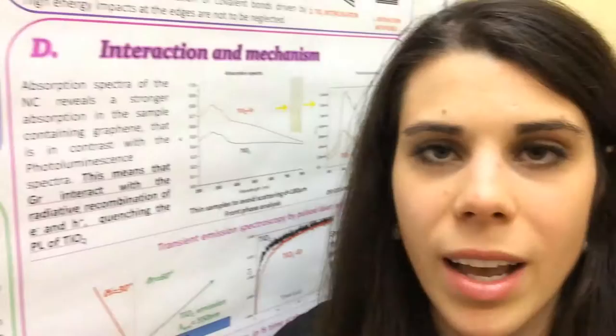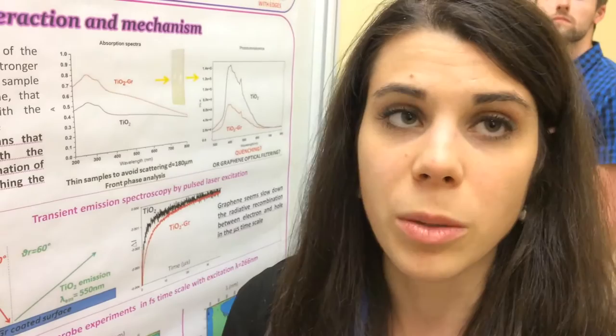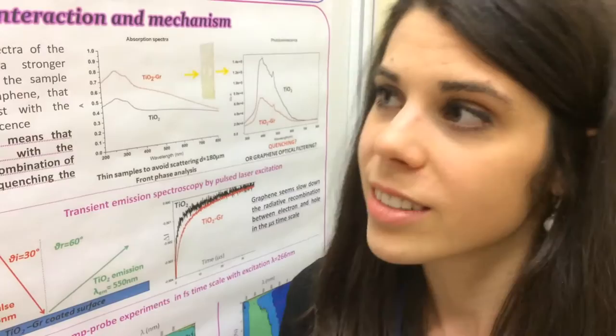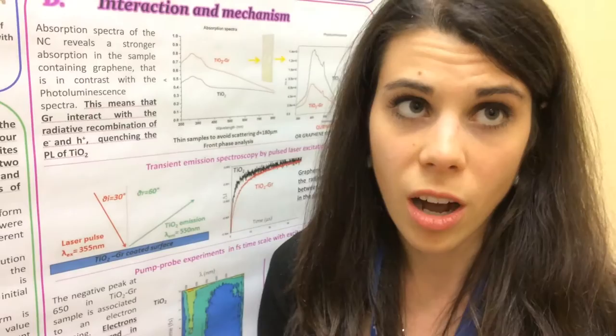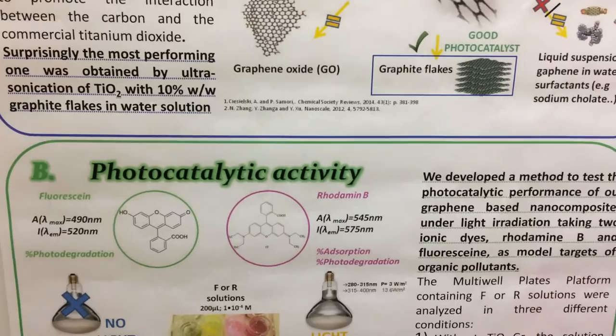Titanium dioxide can easily interact with organic and inorganic volatile pollutants and bring them to photo-degrade. We tried to synthesize the composite with different graphene sources like graphene oxide, reduced graphene oxide, water suspension of graphene, and graphene flakes. In the end, we found that the most promising photocatalyst was obtained by direct sonication of graphite with titanium dioxide nanoparticles in water solution.